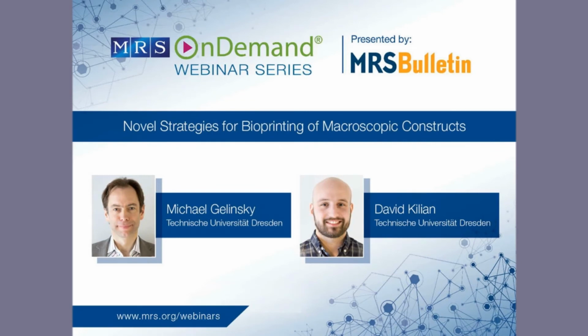Okay, so basically, speaking about the in vitro studies, or most of the studies that we just introduced, they are shown for cultivation over several weeks. So both for mechanical properties, also swelling ratio of the material, strand diameter, so really stability of the material itself, of the 3D construct, but also on the biological side. So basically, people show it for several weeks, and it's also, for example, speaking about the differentiation of stem cells, for example, in osteogenic or chondrogenic lineage. Because we usually work with bone or cartilage tissue or cells, this takes 3 weeks basically. So that's the time frames that are shown in the studies.